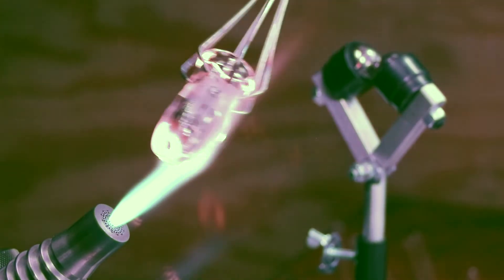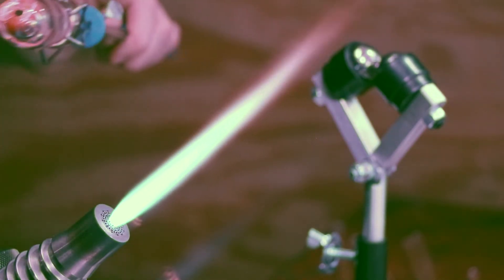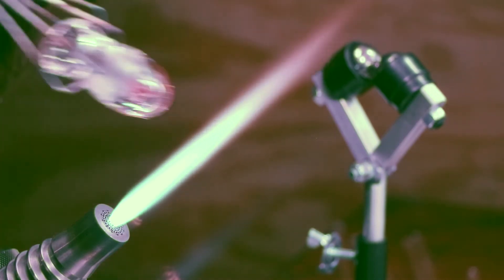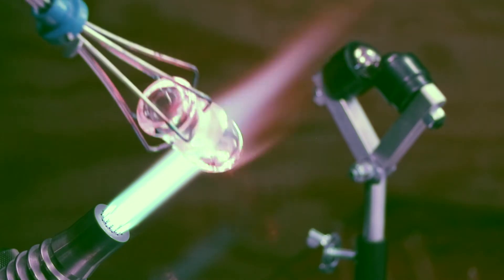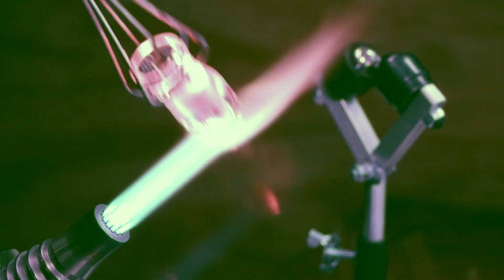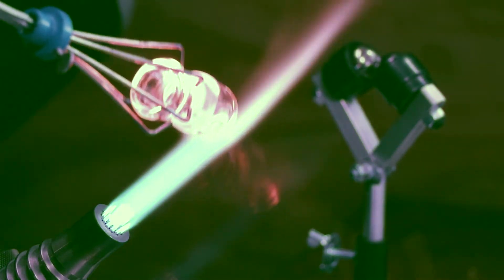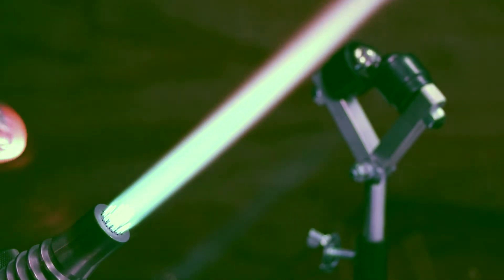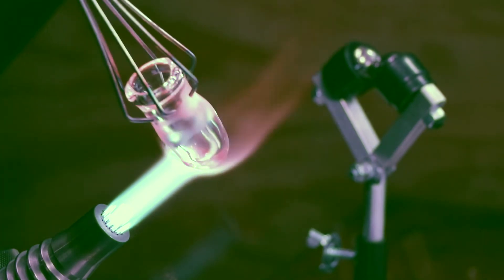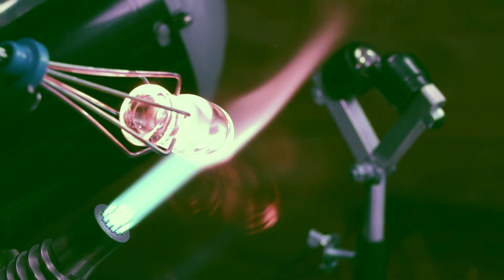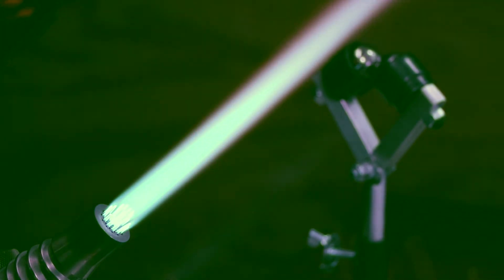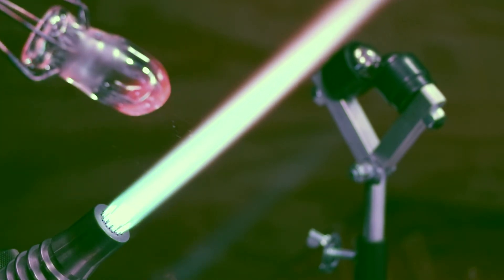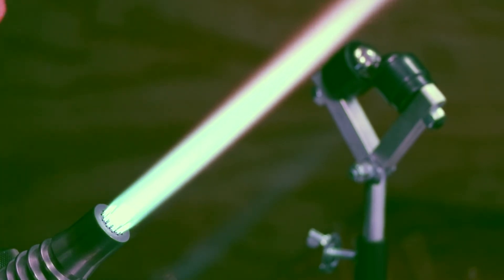At this point, with that really thin area and the surrounding area very thick, just applying heat to that one area, a lot happens. The hole pops open, it ends up enlarging in diameter because the area is very relatively thin. Then once it reaches the thickness of the rest of the tube, it begins to shrink back down. So by just holding it there applying heat, not doing anything else, it goes through a three-step process.